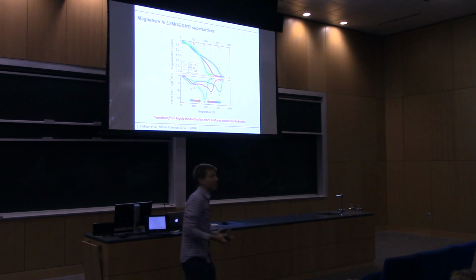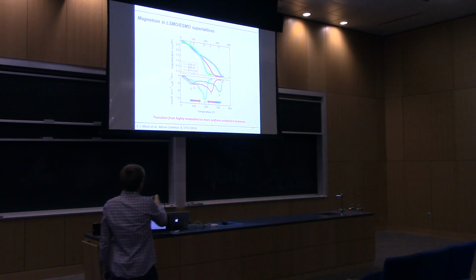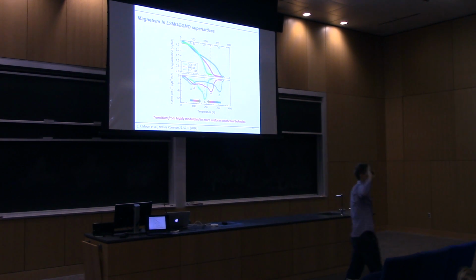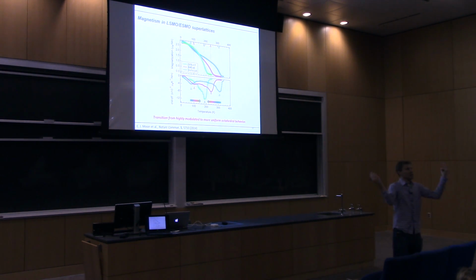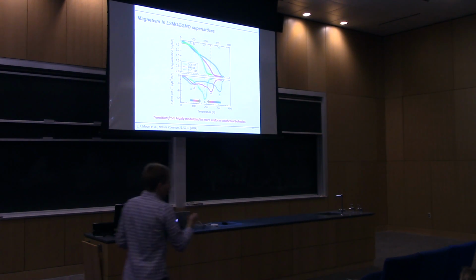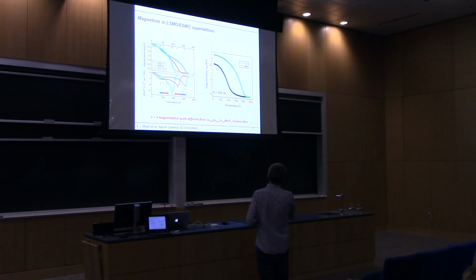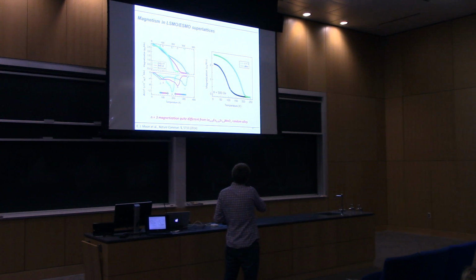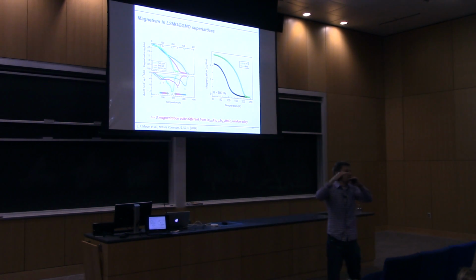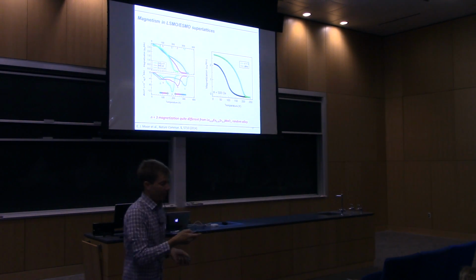And then by the time we go to the 3-3, we see basically one distinct Curie temperature, which is in between that of the LSMO and ESMO. So this suggests that we move from a highly modulated atomic structure with modulated magnetic properties to a much more uniform structure. And you can say, wow, that's great, you just made a random alloy. But of course, we can make a random alloy. We can just throw all the atoms together into the film and measure the magnetization, and the Curie temperature of the random alloy is significantly lower than that of the superlattice. So by making the superlattice, we remove a lot of this cation disorder, and that also helps the exchange interaction and brings up the Curie temperature.